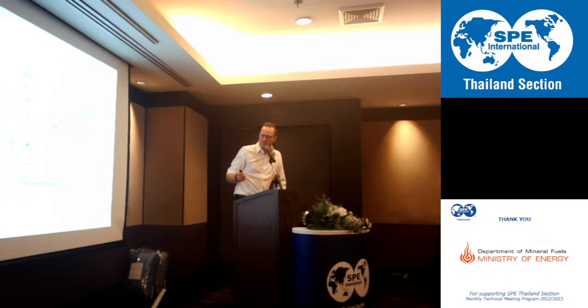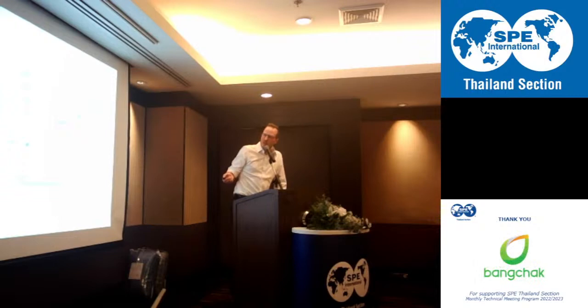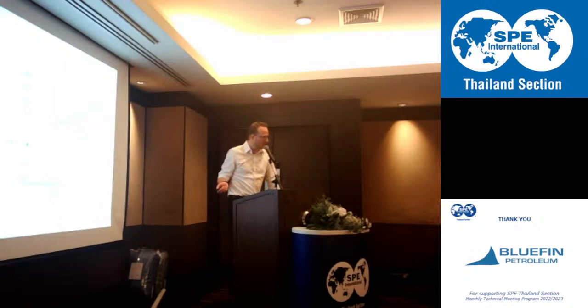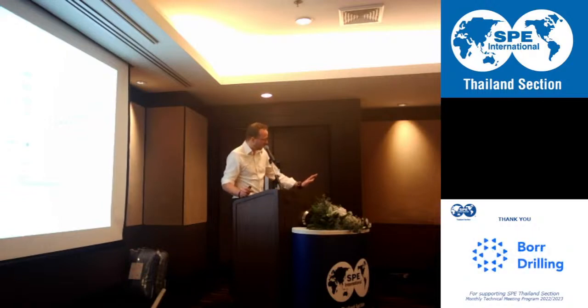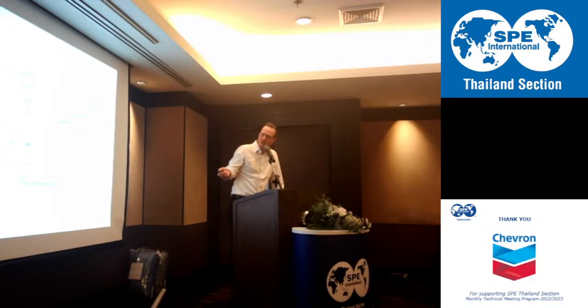This is our probe permeability system that you can see has been deployed on the mini slab. And this is true gas permeability taken with plugs, on the core, okay? So they were cleaned, which is always better compared to the probe permeability that we could have.